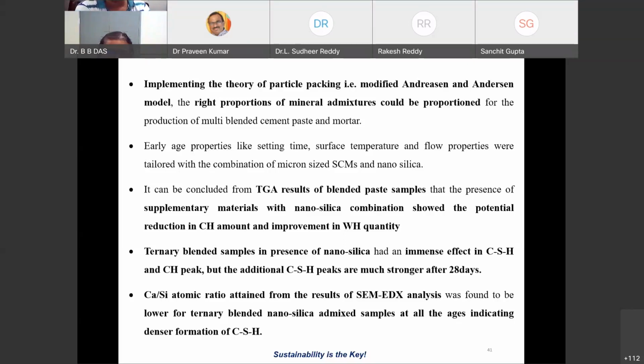Now, particularly the paste samples in the presence of nanosilica had an immense effect on CSH and CH, but additional C-S-H peaks are much stronger after 28 days. This is what we got from the XRD. Then the Ca by Si atomic ratio obtained from the SEM-EDS results was found to be lower for paste samples blended with nanosilica at all the ages, indicating a denser formation of calcium silicate hydrate. We discussed all these.